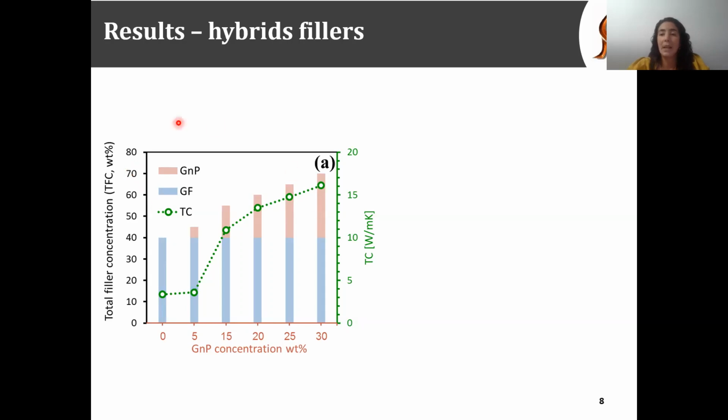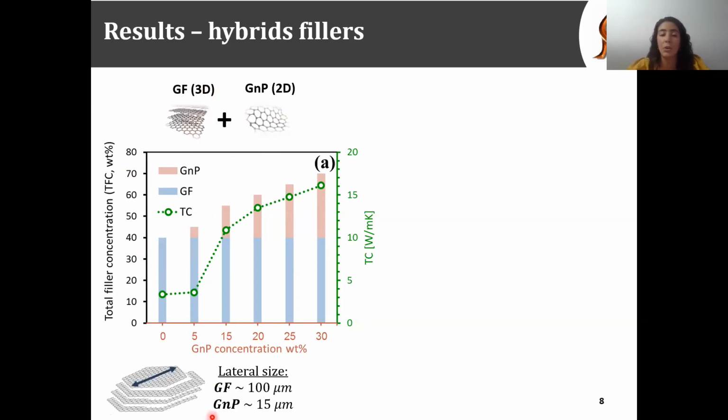A possible explanation for the high hybrid efficiency relates to the synergistic effect between the 2D and 3D network fillers, as well as increasing network density due to the difference in sizes, which leads to less thermal resistance and consequently better thermal behavior.